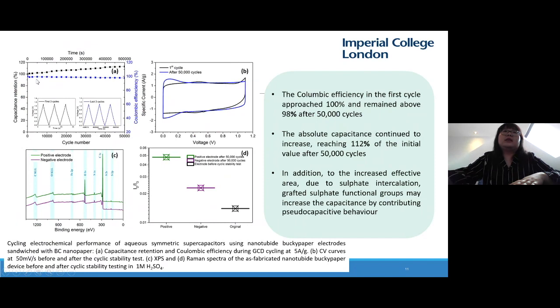ran it in galvanostatic charge-discharge curves for over 50,000 cycles. It showed that they achieve very good Coulombic efficiency, above 98% after 50,000 cycles, and it also shows that it can maintain good stability and really good rate capabilities of the nanotube Bucky paper as well.